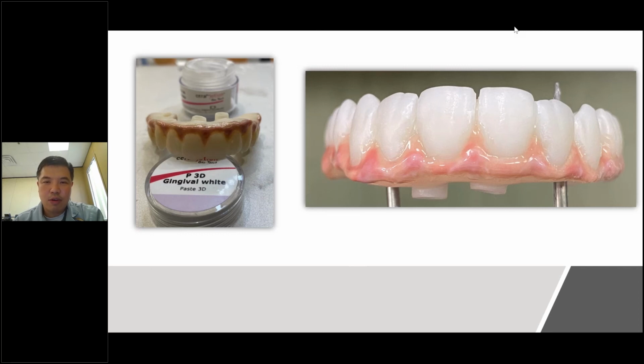So we have to go down to at least a room temperature of 200 degrees before we remove that from the porcelain oven. So for every layer that you apply on here, we take about 3 layers to apply them because we want the colors to be where we want them to be. We have to go in the oven for almost 2.5 hours before it cools down. Okay, so once that's done, we'll go and apply the glaze.